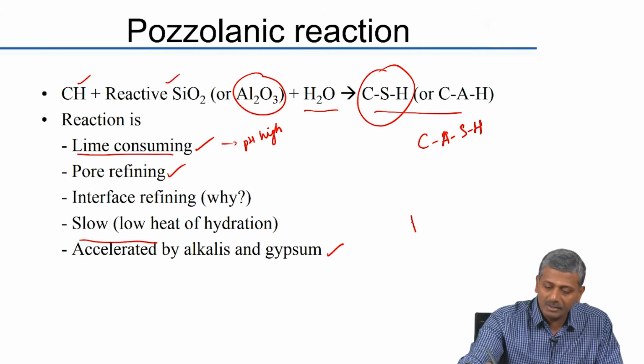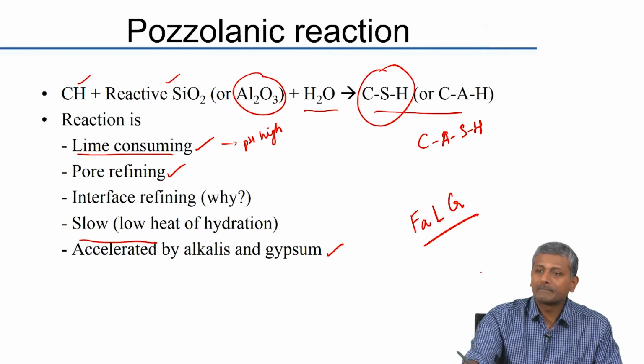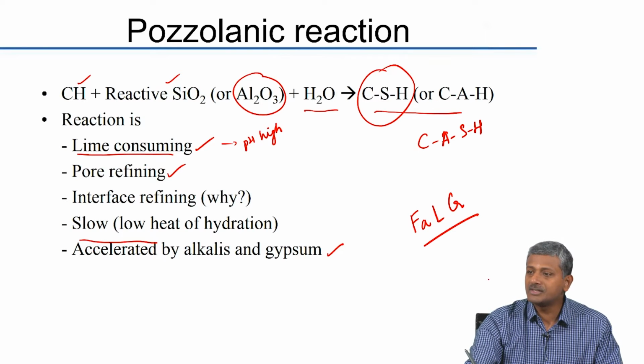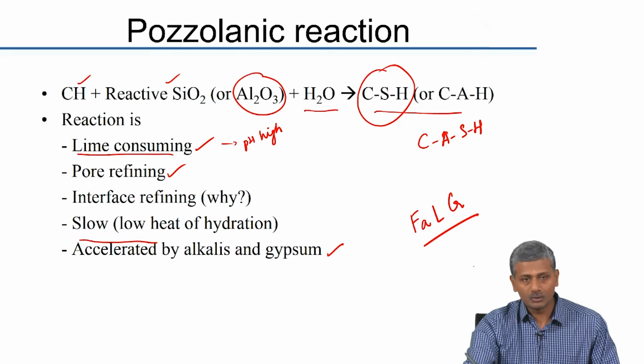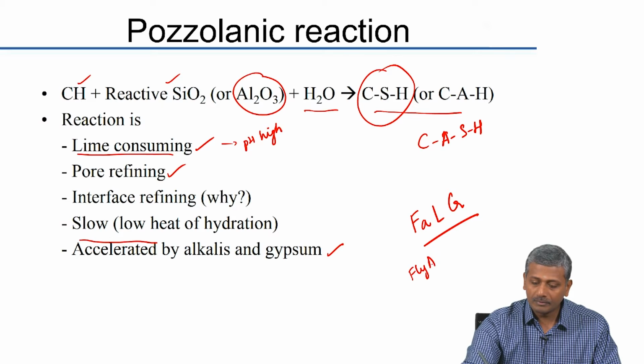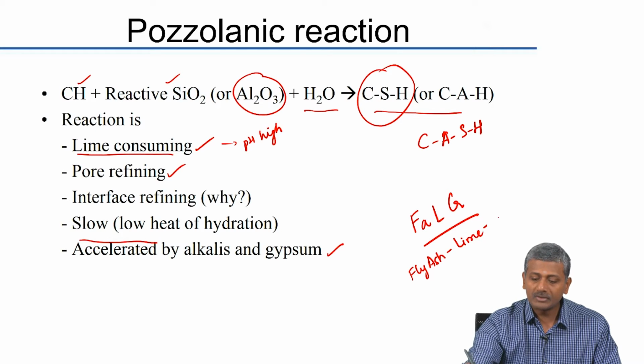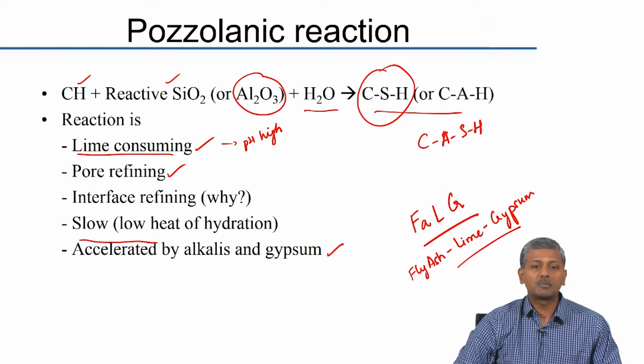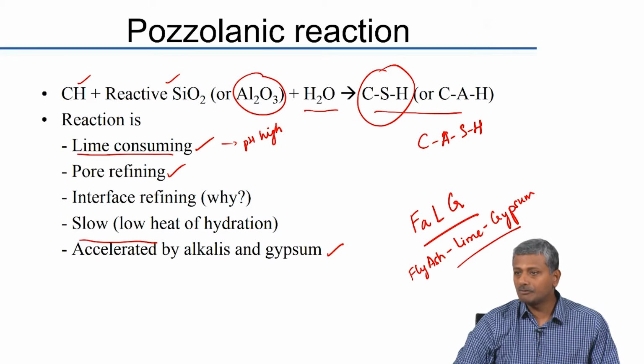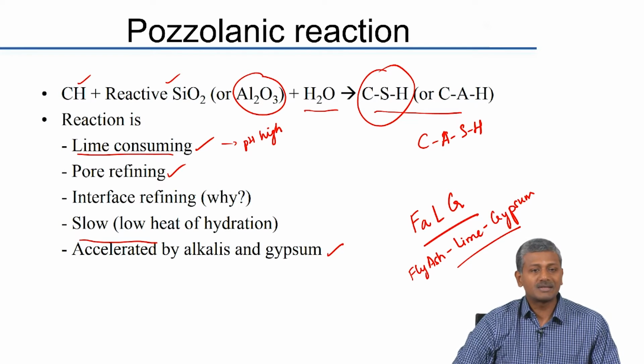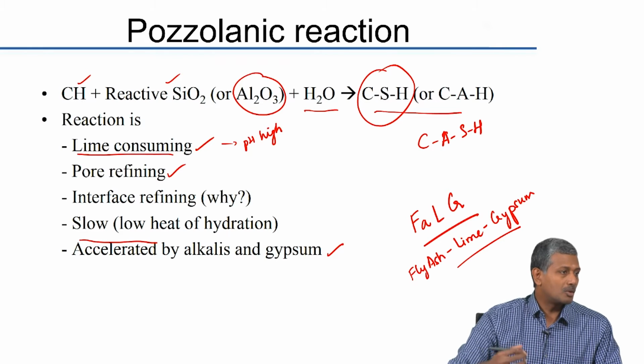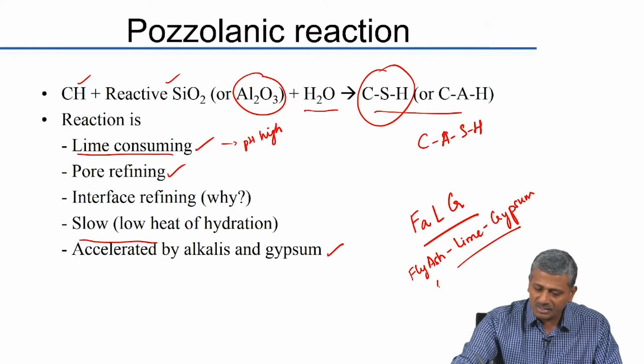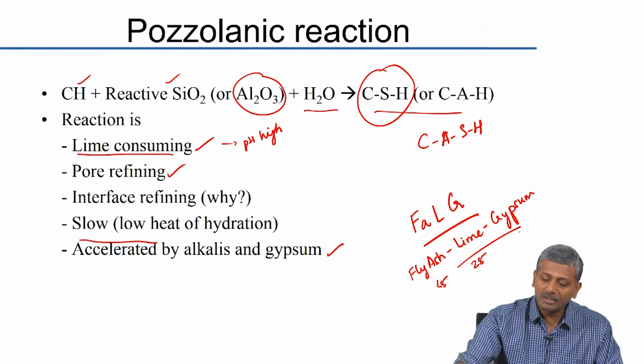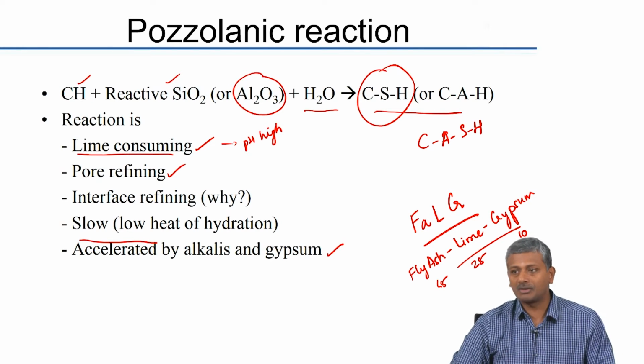Now, some of you may have heard of this technology called FALG. Anybody has heard of FALG? No? FALG is a technology that is being used to manufacture bricks, low strength, not as high strength as concrete, but FA stands for fly ash, L stands for lime, and G stands for gypsum. This FALG technology has been proposed by some researchers as an alternative to clay for manufacturing of bricks. Okay. Instead of burning clay, they say that you can actually formulate the bricks, mold the bricks with a combination of fly ash, lime and gypsum. Approximately it has got about 65% fly ash, I think about 25% of lime and 10% gypsum. That is the approximate formulation, although it may vary here and there.